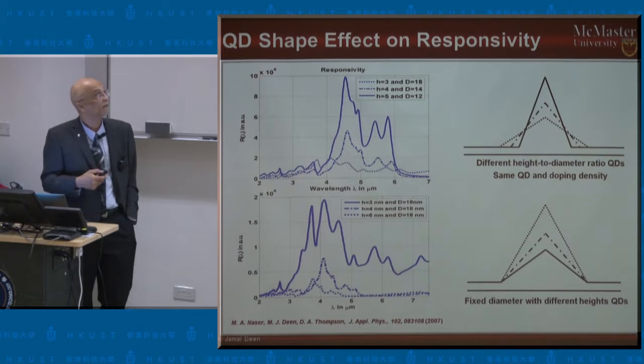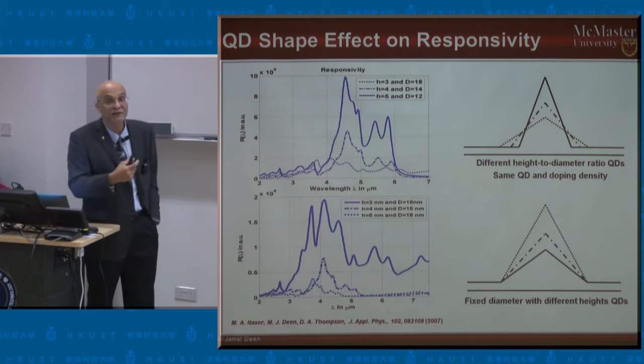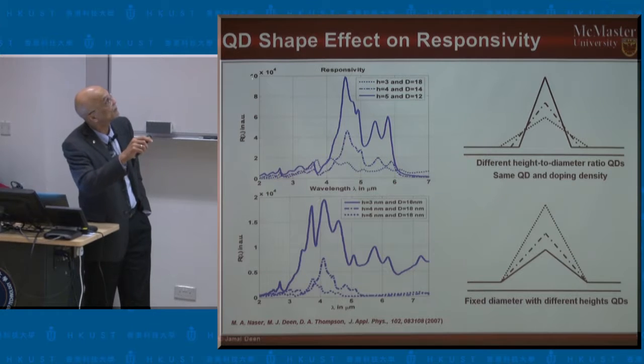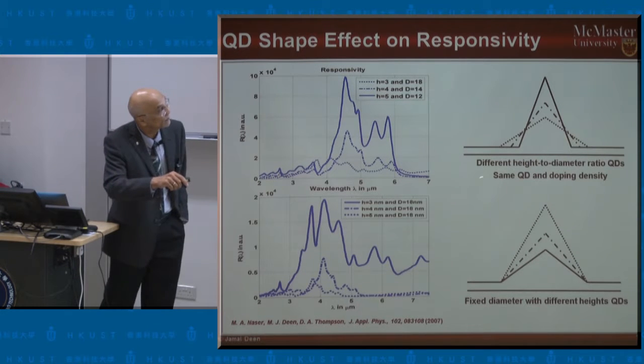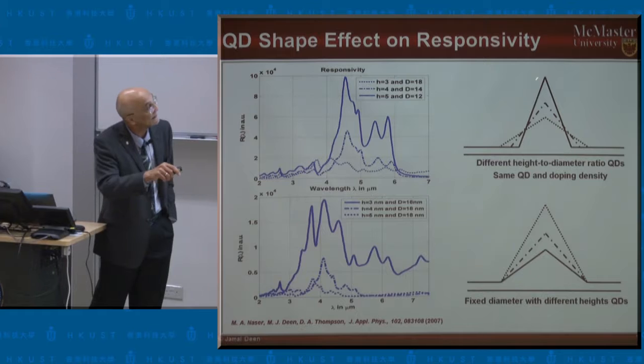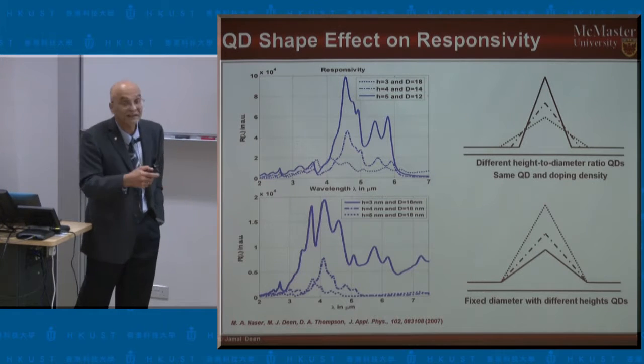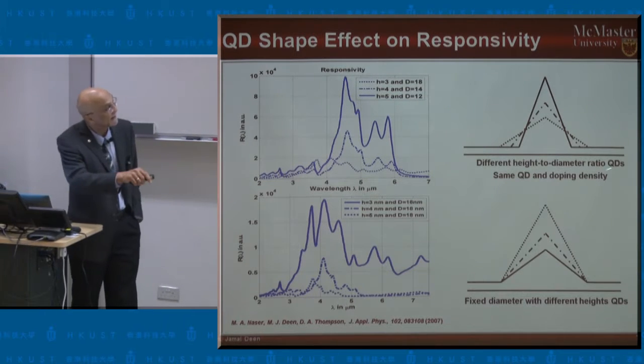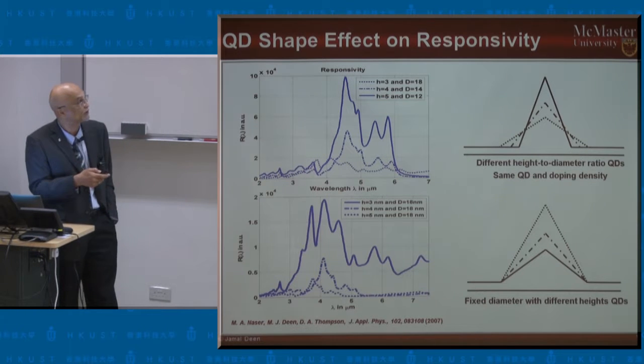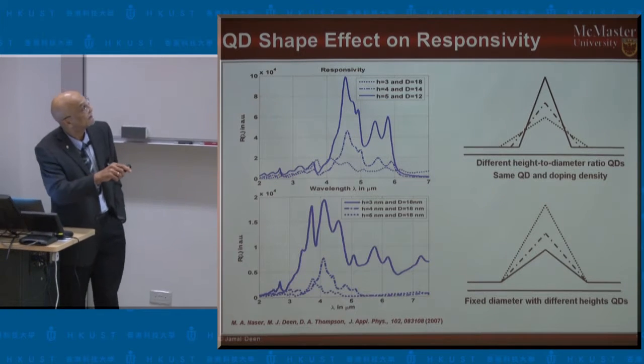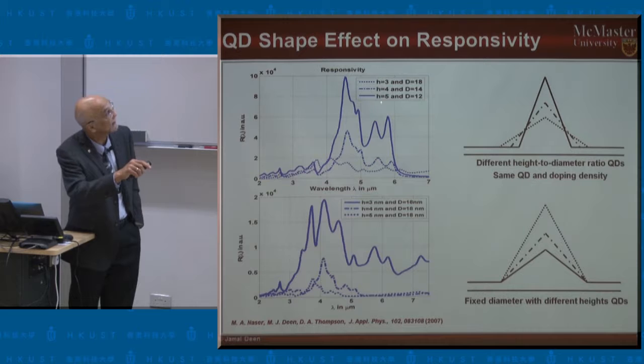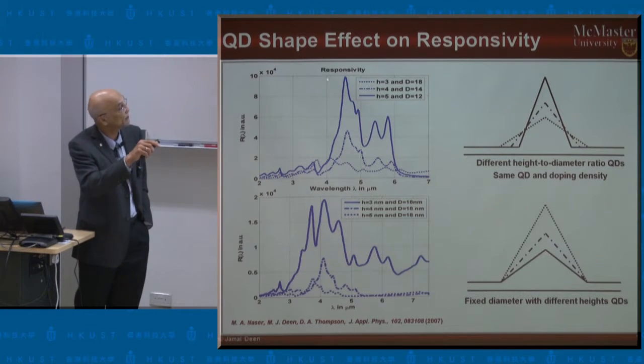We can also do some optimization. So in this case, I just show you a few examples. Here we're looking at the shape effect. What we do is we change the height to diameter, but we keep the same number of quantum dots and the same doping density within the structure. And in this way, we can see, for example, as we increase the height, so from 3 to 4 to 5, we have a better response.